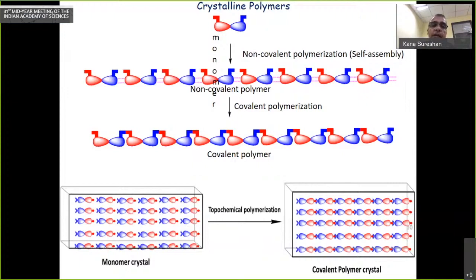So they self-assemble like a chain through this weak non-covalent interaction. Now also you can see two heads, a blue head and a red head, on either side of this dumbbell. And these are mutually complementary reactive motifs. That means if they come closer, they will react automatically and form a covalent bond, a strong bond. So we designed such molecules with these mutually reactive motifs, and we assemble them, by which we will make them come in proximity. This blue head and red head will be at proximity. Then they will automatically react and make a much stronger covalent polymer. But due to the process of this self-assembly, we get an ordered structure.